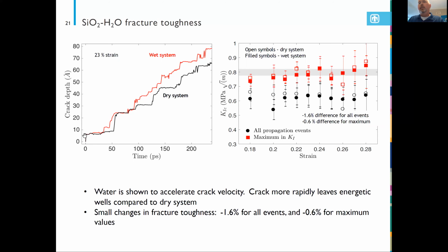But what you'll find is that the dry system actually remains stuck in these energetic wells for more consistent durations of time. So the crack remains localized at a given fixed depth for a duration of time, whereas the wet system seems to not be quite as affected by that. As a result, the crack velocity, which would be the slope in this data, is greater for a wet system than it is for a dry system.